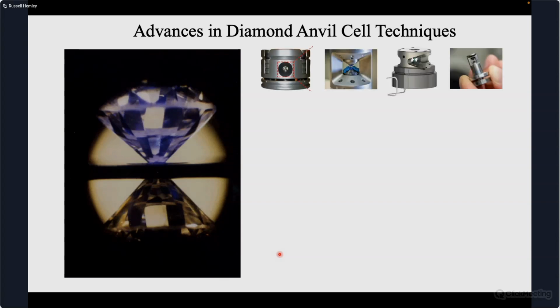So the diamond cell was invented in the 1950s, and all the techniques that we're using for the kinds of experiments I describe, although we use other kinds of apparatus for other experiments, are based on the diamond anvil cell, where we have opposed anvils that compress a sample that's held in place by a metal shim that creates a sample chamber for the system, and a wide range of different designs have been produced. What's notable, of course, is we're dealing with rather small devices with very small samples, because we're generating very high pressures at the very small tips of these diamond anvils.